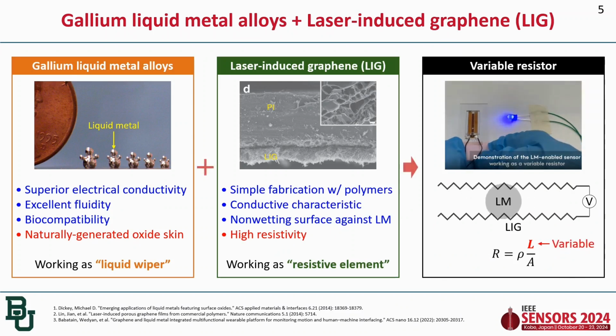Let me slightly change the topic in this slide. Gallium-based liquid metal alloys like gallium or EGaIn are metals in a liquid state at room temperature. They have superior electrical conductivity, excellent fluidity, and are biocompatible, unlike mercury. So we thought that liquid metal is ideal to be used in a variable resistor as a liquid wiper. However, gallium-based liquid metal forms a thin layer of gallium oxide skin in ambient air. This oxide skin sticks to almost any surface. Such a sticky nature of liquid metal has often been considered a significant problem in various applications.